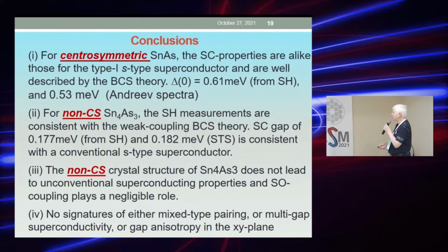And we conclude the anticipated impact of the presence or absence of inversion symmetry, since it is missing in this compound. And for both, there is a nice agreement with the weak coupling BCS theory. We didn't find any unconventional superconducting properties in both the spin orbit and spin orbit missing materials.